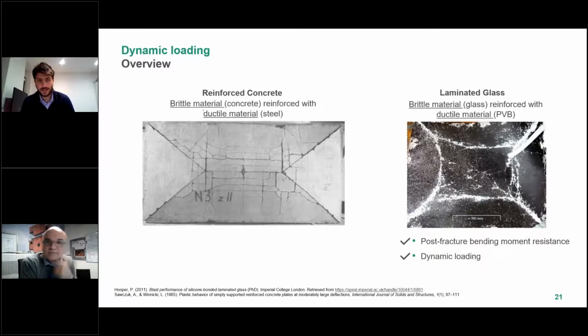Yes, so in my understanding, I think it doesn't. Under blast loading, you will have multiple small glass fragments in each of your glass layers, and where we see the yield lines is where the glass has actually crushed. So this is a step further. First the glass will fracture into smaller fragments, and then it will crush at the regions where you have the highest bending moment or the highest curvature, and this is where you see these yield lines forming. So one way of saying it is that the glass fragment size probably doesn't affect this response, unless the small fragment size results in the fragments delaminating from the interlayer, and then we lose contact. This is the only case where I would imagine that the fragment size is important in deriving the bending capacity.